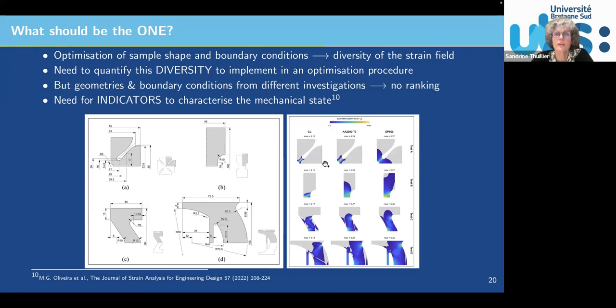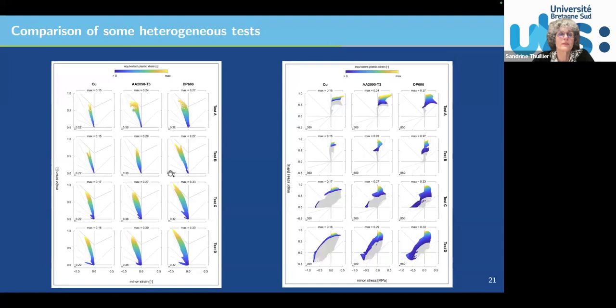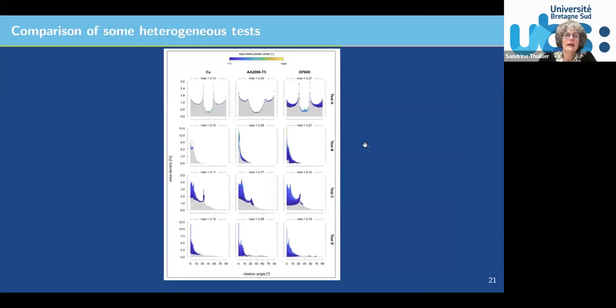So you've got here a distribution. So for the 4 geometries, 1 material, this is aluminum and this is steel. So you've got here the equivalent plastic strain, but you can also plot several other information, like you are here the major strain, minor strain, so you can try to compare the tests. Do the same for the major stress and minor stress. So this gives you information, and you can also, in this case, this is what we call the rotation angle, and the idea is how the information in the test is oriented compared to the rolling direction.